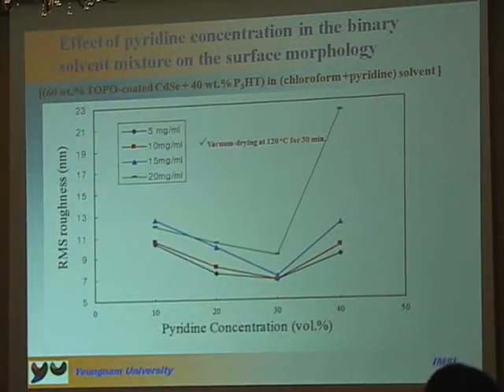So for the binary solvents we use chloroform and chlorobenzene with pyridine. We investigated the effect of pyridine concentration in the binary solvent on the surface morphology. In the figure, you can see that with pyridine around 20 to 30% in the binary solvent, we get very low roughness. But with more than 30% pyridine concentration in the solvent, we get very high roughness.